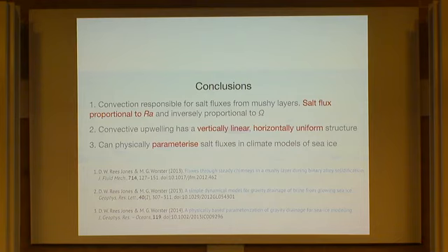If you use one of these bulk permeability formulae, you predict Rayleigh numbers which are of order 100, but it's very sensitive to what you put in about the permeability of the ice. These field experiments were quite novel. In order to measure things in situ and get some handle on the porosity, they froze in a set of platinum wires.